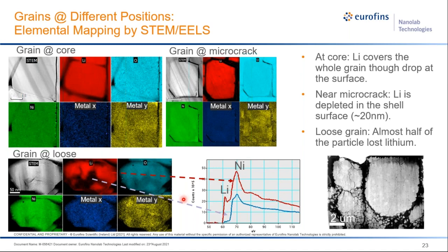EDX can detect most elements, but some very light elements — particularly lithium — cannot be detected by EDX in most cases. That's why we use EELS (electron energy loss spectroscopy). EELS is an advanced but very powerful technique. Here, showing several grains at different locations within a secondary grain — from the core area — we can see that one primary particle has lithium covering the whole grain, though the intensity drops at the surface. For a grain near the crack, in the shell area, lithium has essentially disappeared. For another grain, almost half of the lithium has been removed — a clear result of degradation.